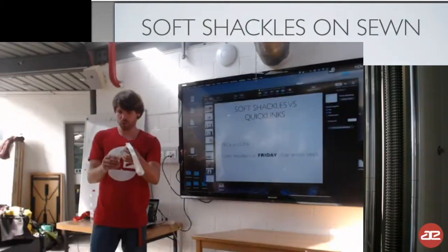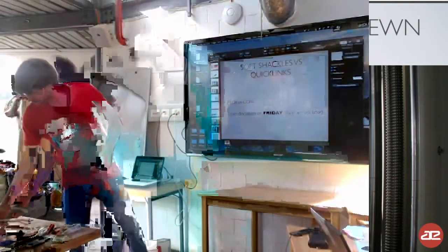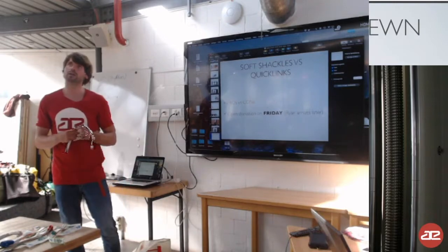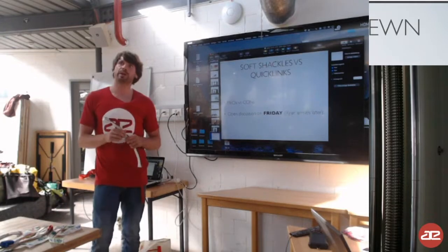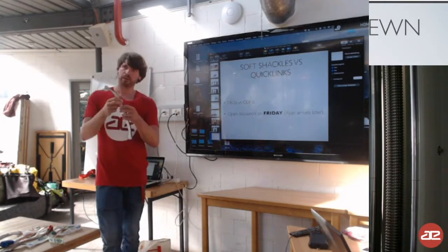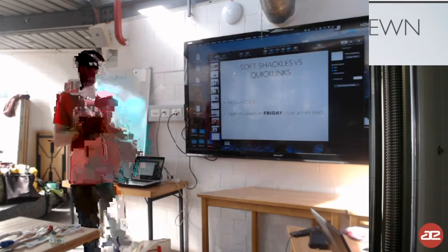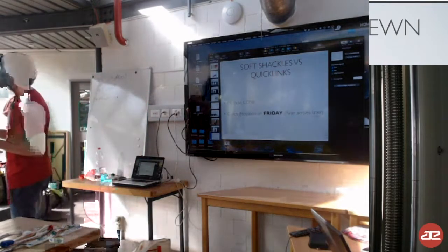This is the webbing that broke the padded loop at about 17 kilonewtons. The loop was padded, the soft shackle was not padded. How strong is the webbing? The webbing is 24 kilonewtons. Have you tried it with the shackles? Same means that if we use a shackle, the webbing breaks in the stitching part. So definitely stronger, much stronger, like at about 21, 22, something like this. And what did it break at with the soft shackle? 17 point something. That's fine.